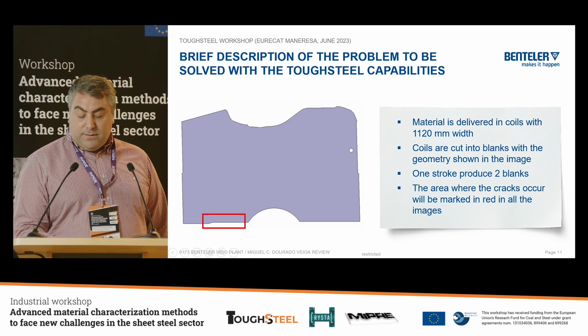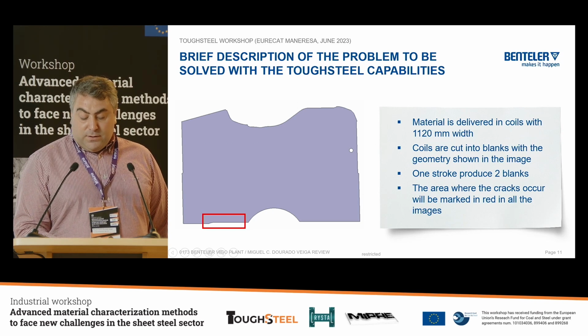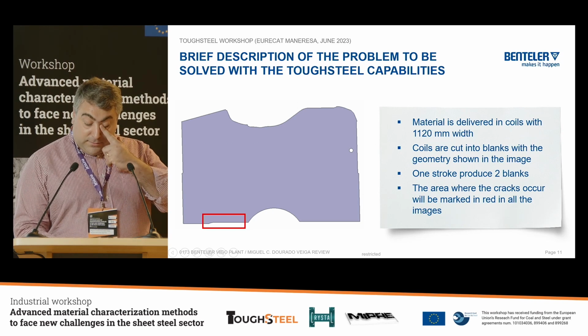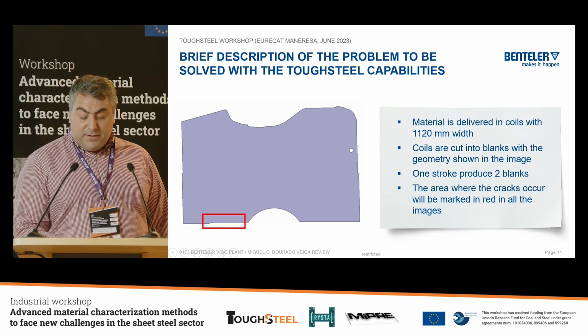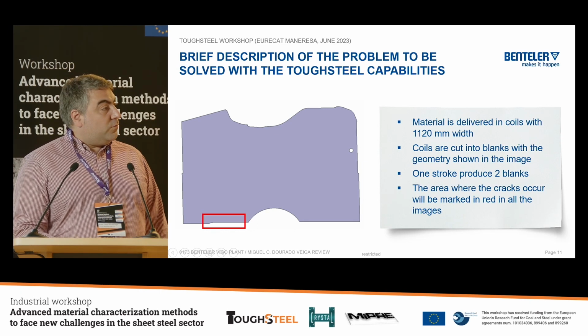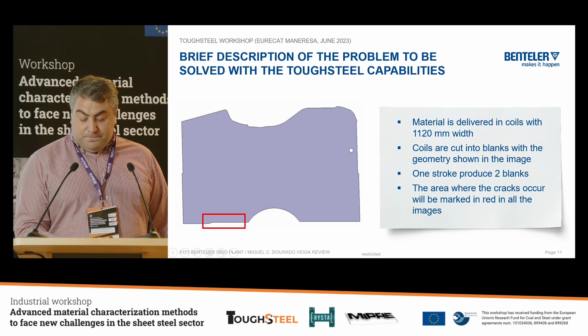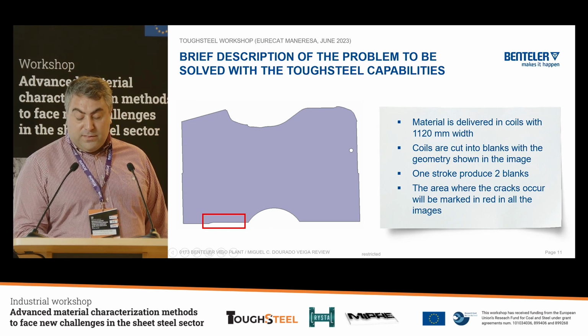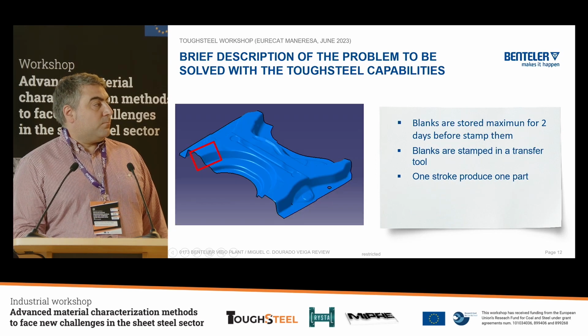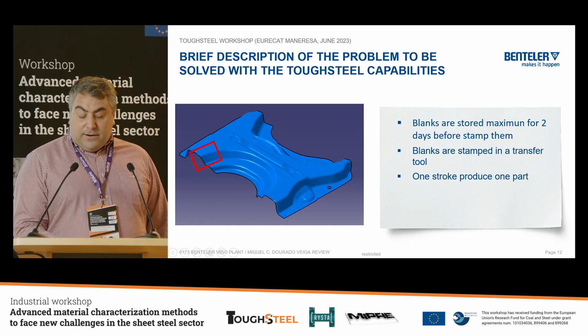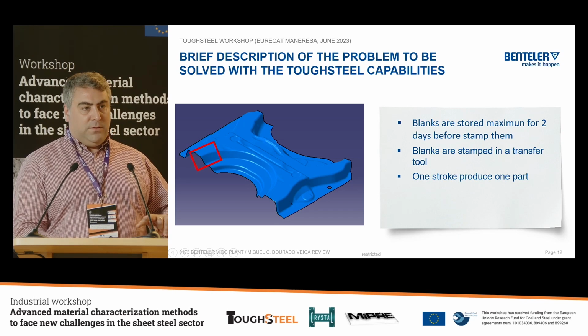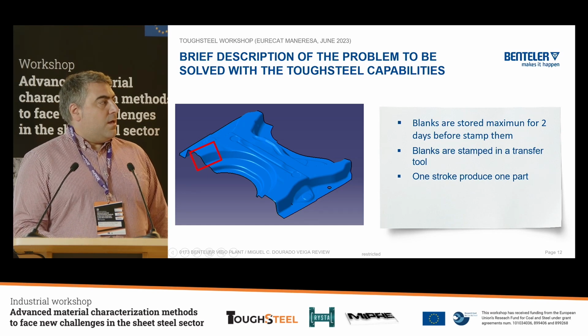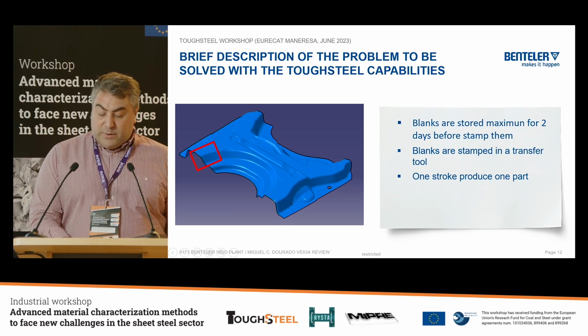The material is delivered in coils with 1,120 millimeters width. Coils are cut into blanks with the geometry shown in the image. One stroke produces 2 blanks, and the area where the crack occurs is marked in red in all the images. Blanks are stored a maximum of 2 days before stamping. As I said, we have 2 processes. First, we cut the blanks from the coil, and after that, we stamp them in another press.